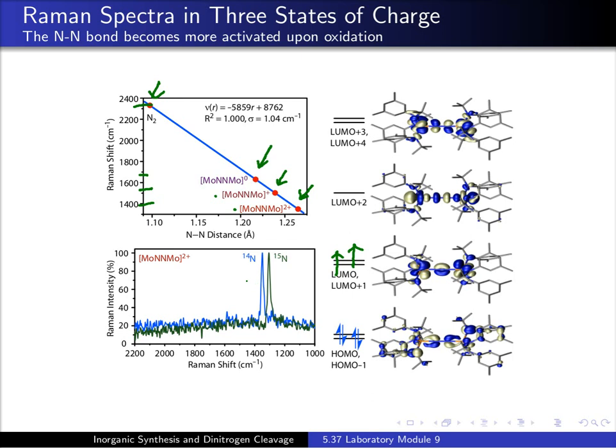And what you're seeing on the bottom is one of these Raman spectra where we were getting the data for the NN stretching frequency, and you can see that when we're using natural isotopic abundance nitrogen, we get the peak right here, and if we use N15 labeled dinitrogen, that peak shifts further to lower energy due to the heavy isotopomer, the N15 isotope present in the NN oscillator. And so we can conclusively assign this peak as due to the NN stretching frequency, because when we synthesize the complex using N15 labeled N2, that band shifts in the expected direction and by the expected amount.